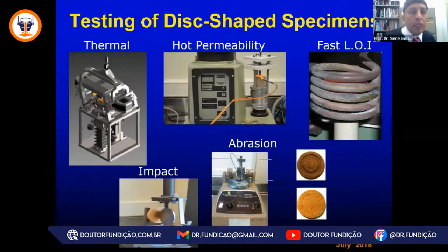On this slide, I'm showing the new standardized disc-shaped specimen testing technologies: the thermal distortion, the hot permeability test, the fast LOI or loss on ignition test, the impact test that we use for measuring the retained strength on our sand, whether it's a newly developed chemically bonded sand, or after that chemically bonded sand has been exposed to heat, we can measure the retained strength to understand if we can shake out that casting from the chemically bonded sand mold.